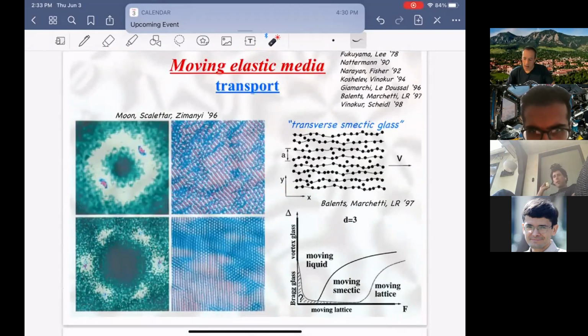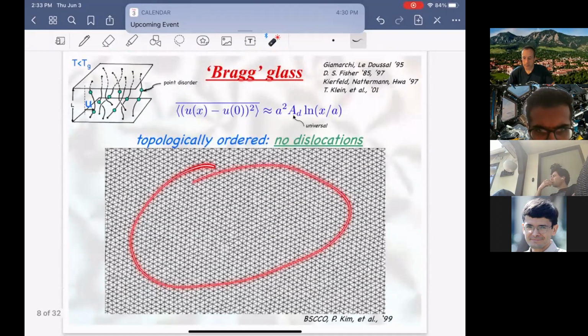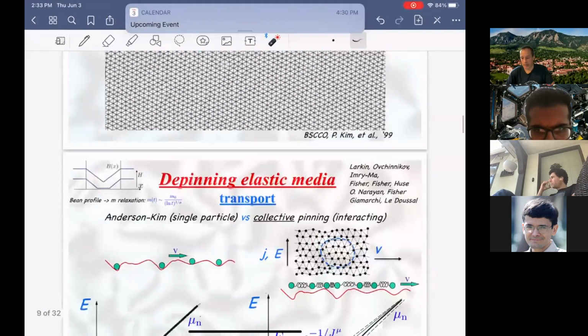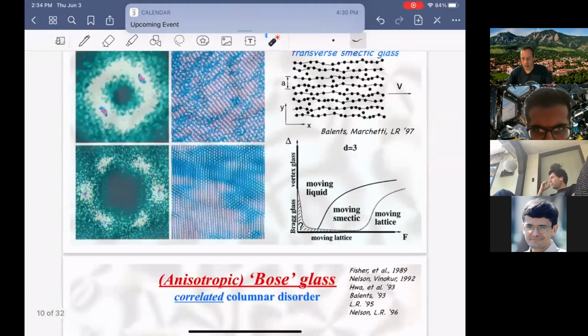Well, you can think of it as an observation that you start out with a state that has periodicity, at least short range periodicity, in all directions. So it forms a triangular lattice, or a state like this, which is distorted by disorder, but it still has short range periodicity in all directions, and that is described by 6 peaks. But when you begin to move this medium, it melts, but then it reforms into something that still maintains periodicity in a transverse direction, but no periodicity in the direction of motion. And that's the transverse smectic, indicated by these 2 Bragg peaks.